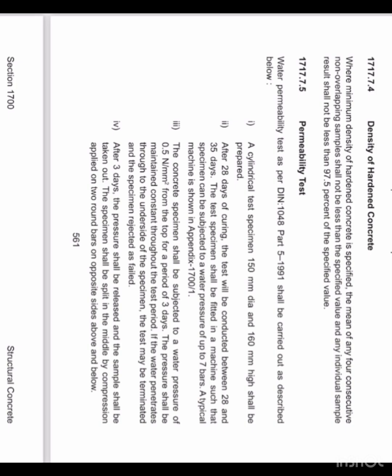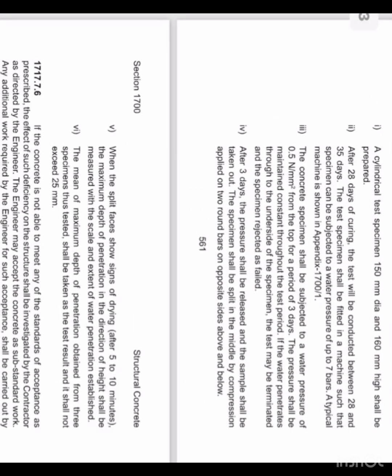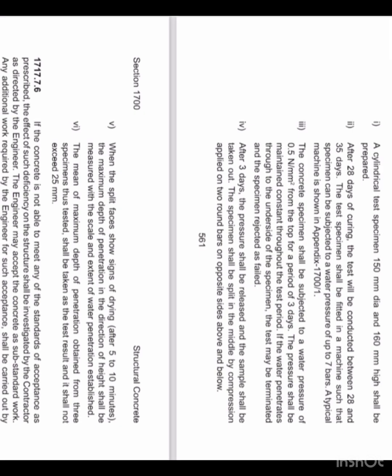1700 by 1. The concrete specimen shall be subjected to a water pressure of 0.5 N per mm square from the top for a period of 3 days. The pressure shall be maintained constant throughout the test period. If the water penetrates through to the underside of the specimen, the test may be terminated and the specimen rejected as failed. After 3 days, the pressure shall be released and the sample taken out.